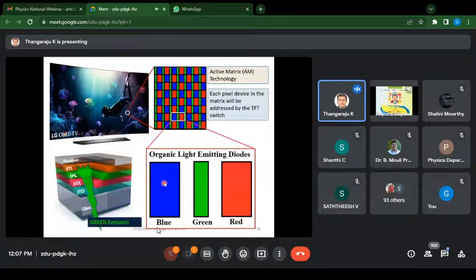Here you can see that the arrangement will have the three primary color light emitting diodes. Each diode will have the typical layers of organic molecules for hole transporting, electron transporting, and light emitting. These organic thin layers, of thickness around 60 to 100 nanometer or even less, would be sandwiched between the transparent anode and the cathode, most widely used silver or aluminum cathodes. So this is the typical structure of the organic light emitting diodes used in displays.